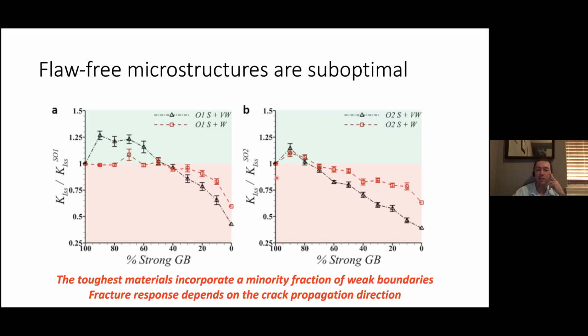This is for orientation 1. For orientation 2, we see a similar trend. Here, the sensitivity to the weakness of the weak grain boundaries is not as pronounced, but you can still see that the optimal toughness is reached when you have 10% admixture of weak grain boundaries. And in this range, the toughness increases as you make the boundaries weaker.